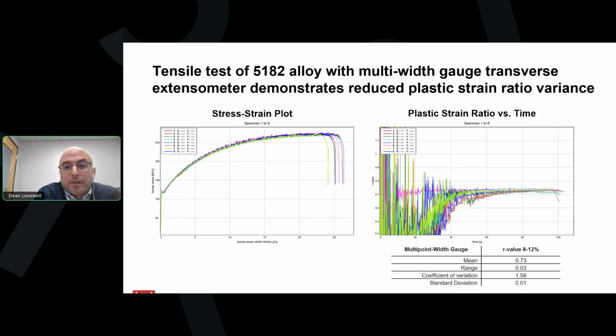So now let's look at the effect of using this method. Although we still see some of the characteristic jerky flow in the stress strain plot, the important thing is that the oscillation in the plastic strain ratio has been dramatically reduced. This is because the transverse extensometer is now taking into account the localized width strain across the reduced section and averaging it into a single result.